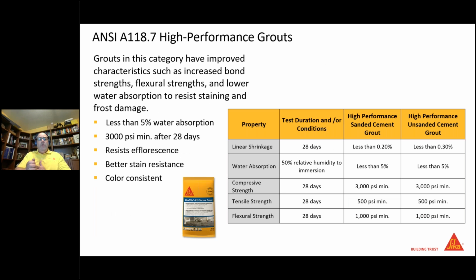So when we look at high performance grouts, ANSI 118.7 designation. So what does this tell us? If we look at this graph, we're going to skip some of these, linear shrinkage, but what I really want you to see is water absorption. If you look at that water absorption, the test duration and conditions is 50% relative humidity to immersion. So with that being said, this grout has to have less than 5% absorption in the sanded or unsanded. So there's still some absorption there, but with a higher performance, more denser product, it is down to less than 5%. Those 118.6 grouts are going to be at a higher absorption.